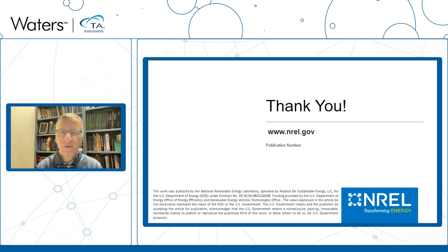So that's a very good question. For much of what we end up doing, the major components in our materials are actually the materials that would be currently employed in making those networks. So we're adding very little cost in those cases. For example, polyethylene networks are currently made by reacting polyethylene with dicumyl peroxide in a reactive process. In our particular case, we take polyethylene and react it with dicumyl peroxide plus a little bit of this bitemps methacrylate molecule added into the system.